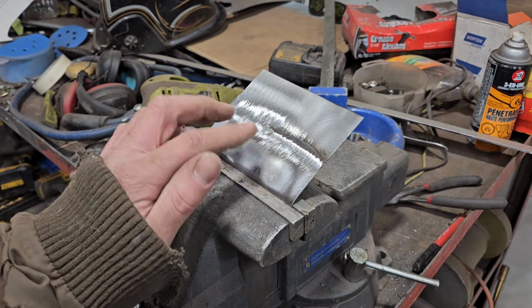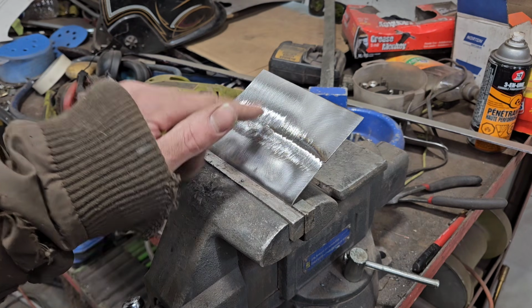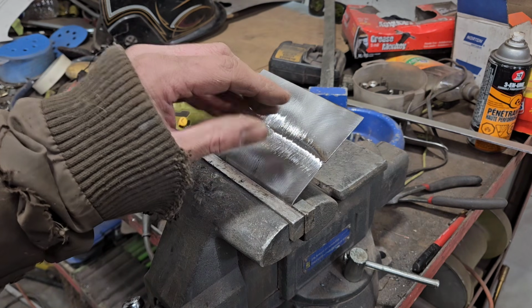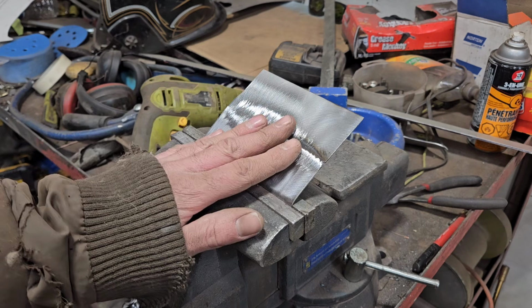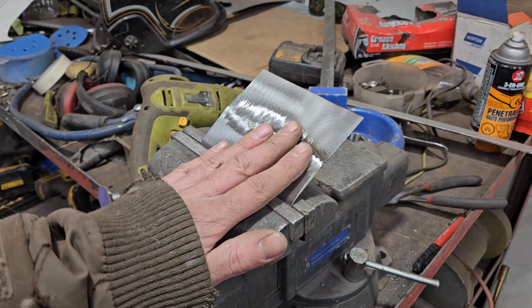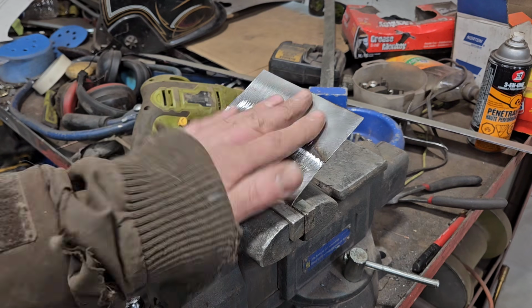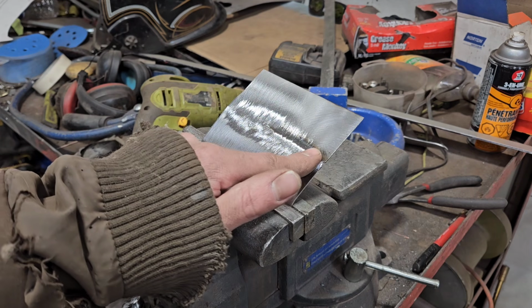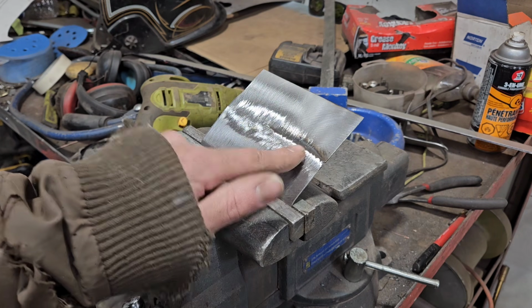That's where your warpage comes from. So the more you weld on it, the more chance of that panel is going to warp and get away from you. Not only that, but grinding also adds heat to the metal. So welding, grinding, welding, grinding, welding, grinding, it's adding more damage, more chances for that to get away from you.